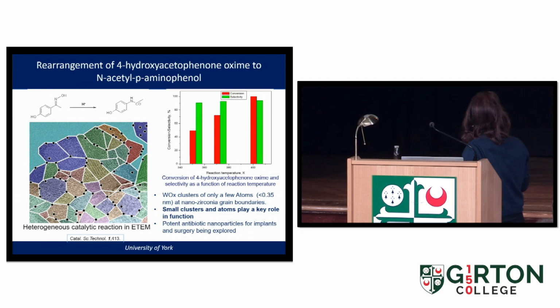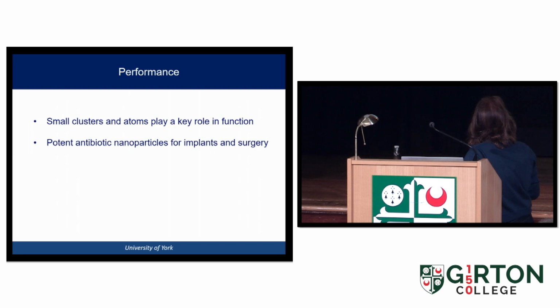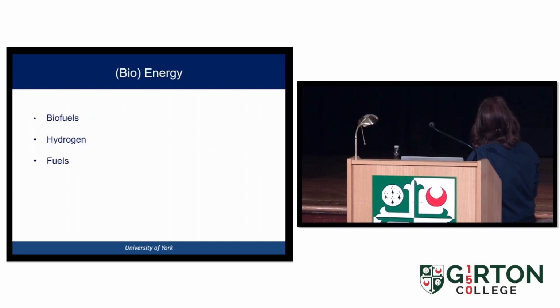Under these conditions, we get very good product. You can see almost 98% product. So small clusters and atoms seem to play a key role in the function of this catalyst. And we're using the same technology to synthesize potent antibiotic nanoparticles for implants and surgery. So that's where it's heading.